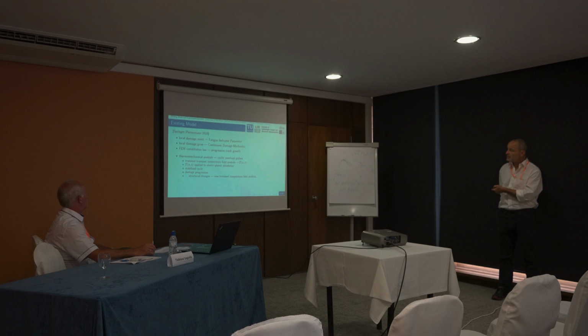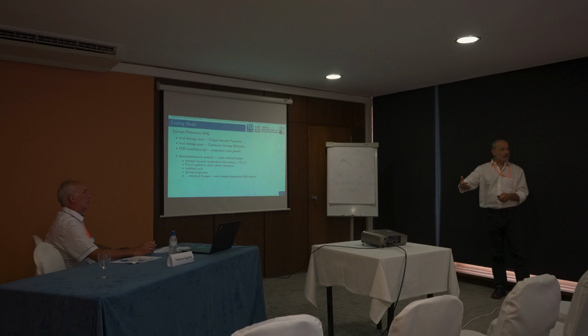So, existing model, what do we have for modeling and simulation? This has been published earlier. We have a local damage onset, which is based on a fatigue indicator parameter and the Fatemi-Socie law. Then we have a local damage growth, which is based on continuum damage mechanics, locally increasing damage and material degradation. And since this is implemented into a finite element code, we can model crack nucleation, fatigue crack nucleation, and fatigue crack progression in a structure.